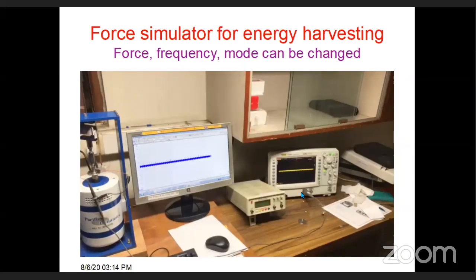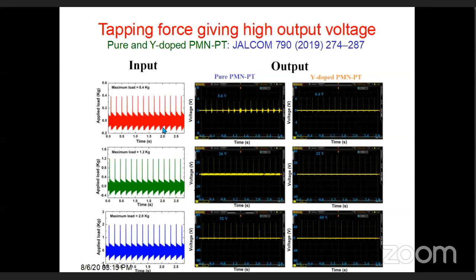If you increase the force applied on this from 0.4 kg to 2 kg, you can find this output voltage is changing from 3.6 volts up to 60 volts, and these gaps are 1 second gaps. So the frequency in this case probably is 1 second.